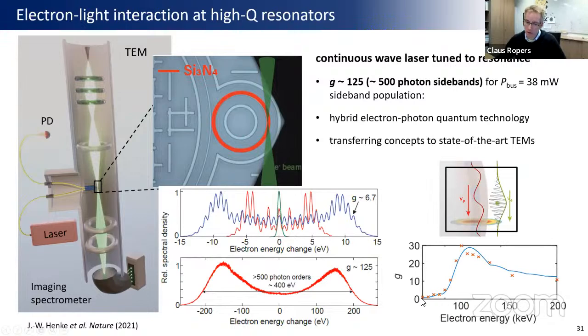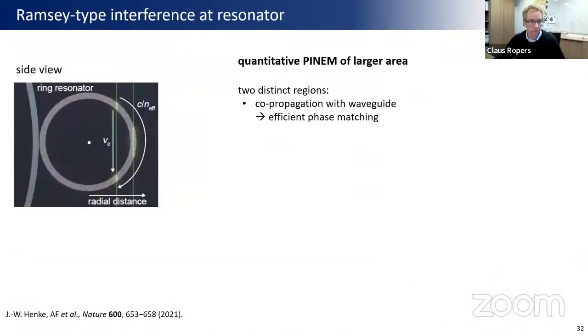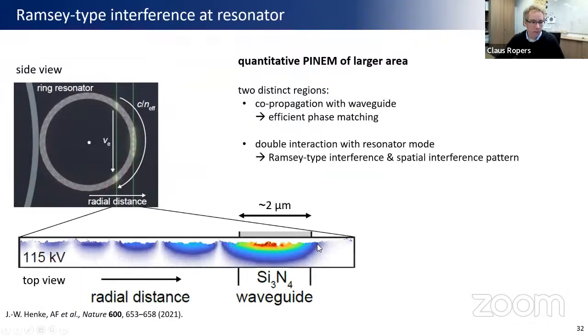Okay, we've also characterized this actual phase matching. So the electron velocity, of course, changes with changing the electron energy. And there's a peak as expected, so simulated and experimentally measured, in this vicinity of 100 kiloelectron volts. Okay, we can now scan the electron beam at different energies and actually map out these mode profiles here.